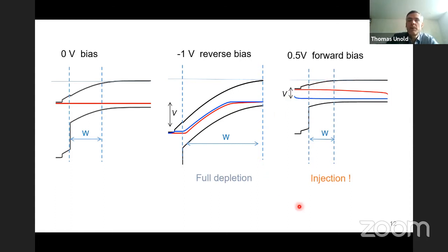And this is what people have done for many years in many materials, also chalcopyrites and thin film silicon and cadmium telluride and so on. And in principle, this is okay. You can see here, the depletion region got smaller. Now it's smaller than the device thickness. You think, okay, this might be okay.